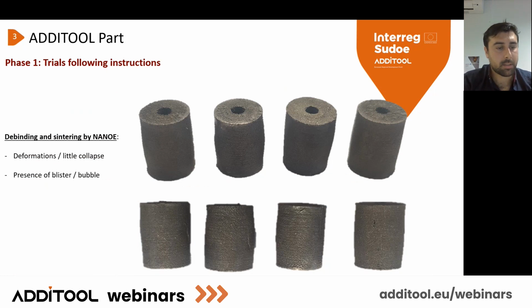Because we are not able with this cubic oven to perform it, we called Nanoe. This is a supplier of the filament, and we printed several samples like this. It is about 20 millimeters of height and only 15 millimeters of diameter. And with the supplier also, with this kind of little part, we have still deformation and little collapse, the presence of blisters, bubbles, etc. So this kind of filament, even with the curves that the supplier gives us, doesn't work as we want.